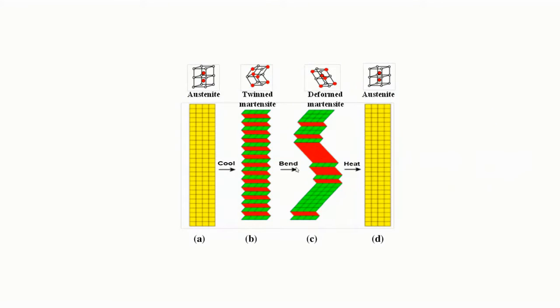And when we are deforming that, applying any kind of loading, in this case it's bending, but you can simply stretch it under tension or compression, we can get the deformed martensite, and the detwinning also is happening over some stretch. And finally, if we are heating, we are again getting back the entire initial structure as austenite, and this entire deformation can be recovered completely.